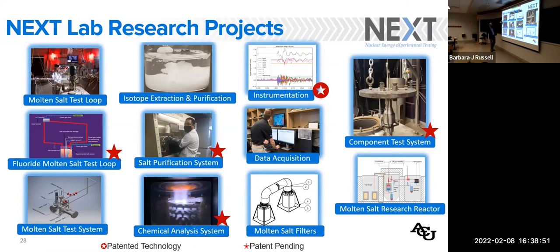So we have the molten salt test loop. It's about a 5-gallon system that uses a low melting point salt. And that was our first molten salt system. And we made lots of mistakes, or learned a lot from building it. Our second, a higher temperature fluoride salt system, operates up to about 350 degrees centigrade. This system will operate up to 725 degrees centigrade. Both of these are about 5 gallons of salt. This system is about 2 months away from being commissioned.